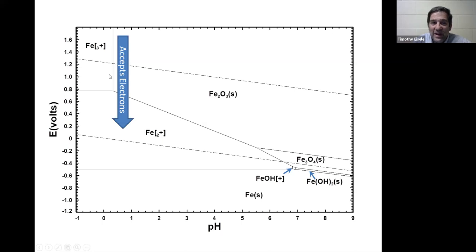So whereas you would have needed pH right around 0.5 to dissolve iron in the +3 state, which is very concentrated, very dangerous acid, in contrast, we can dissolve the Fe2+ under conditions that you could bathe in without getting any acid burn. So we can see there's an advantage here to making sure it's in the reduced form if we want to dissolve it.